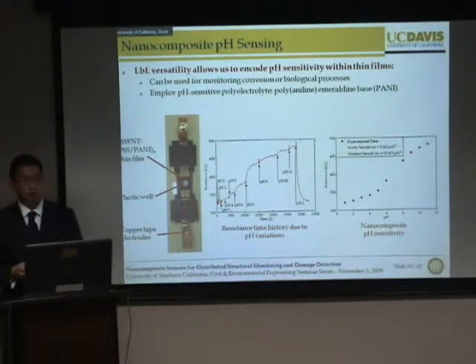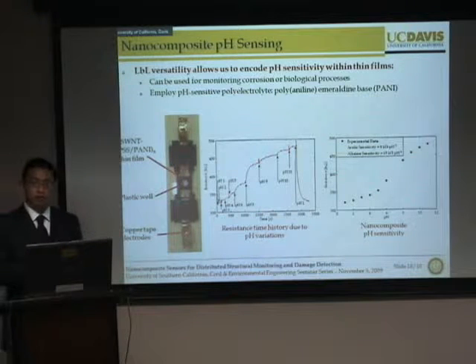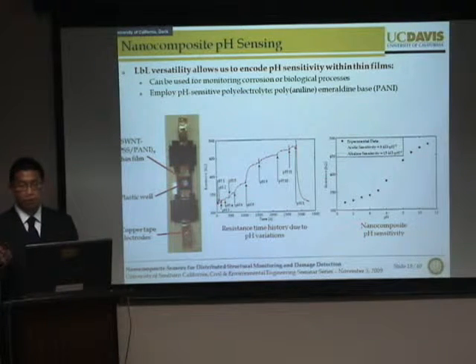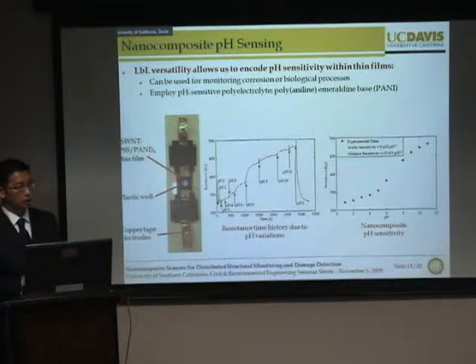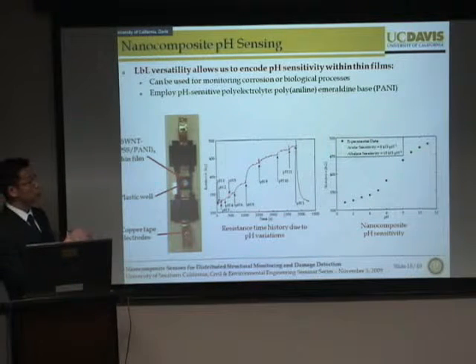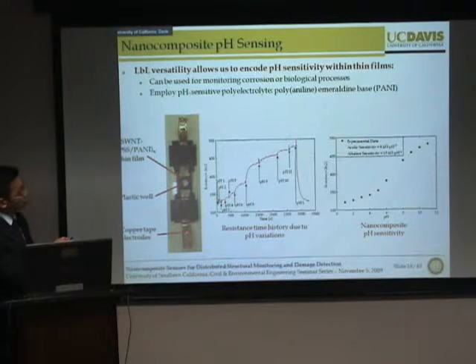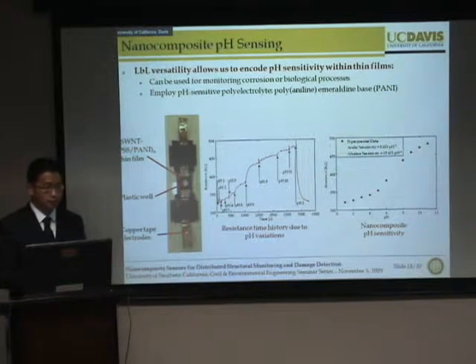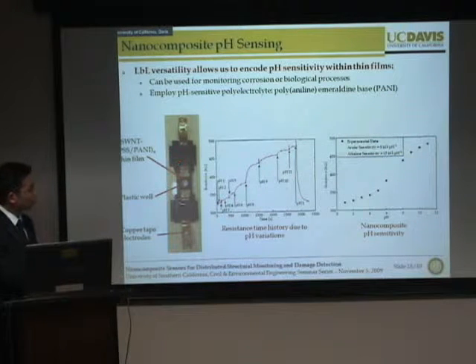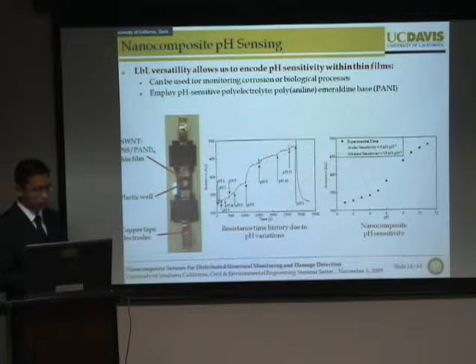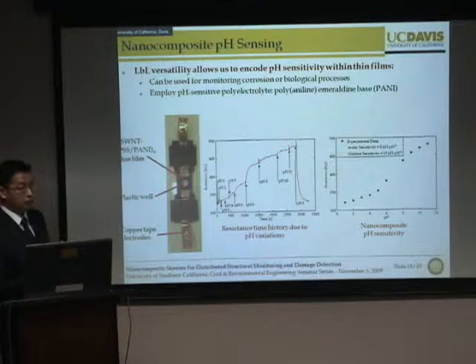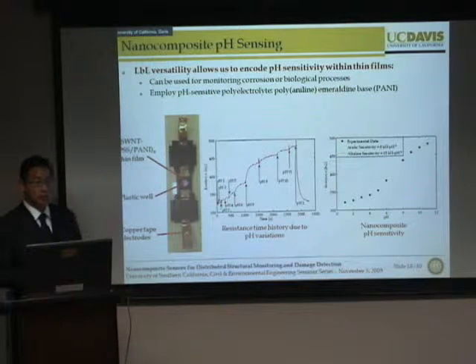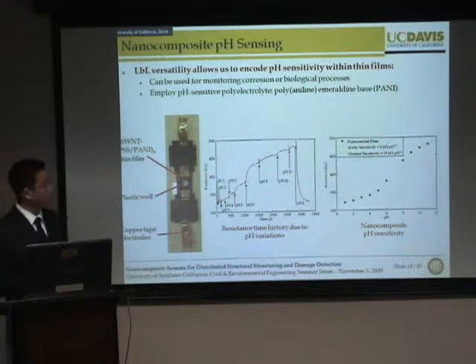Now, as I mentioned before, with this type of layer-by-layer thin film fabrication system, we have the ability to encode different sensing mechanisms within the material itself. So instead of using polyvinyl alcohol, we can replace that with a pH-sensitive polyelectrolyte known as polyaniline and basically create our thin film nanocomposite again. So here, the objective is to develop a pH sensor that we can use for biosensing applications or even to detect the onset of corrosion.